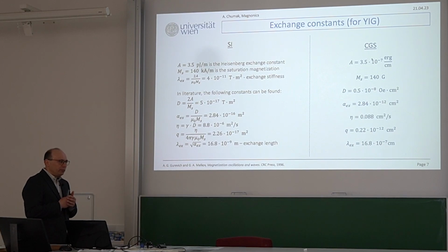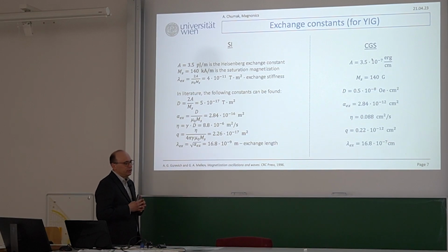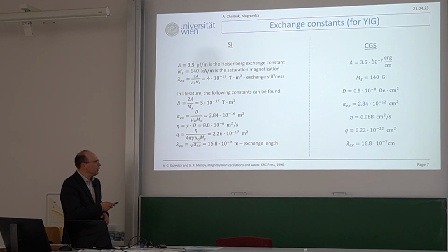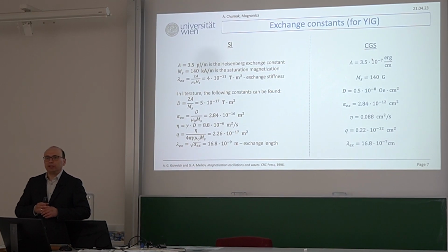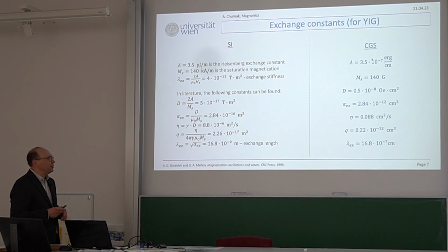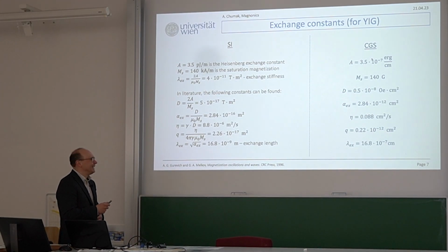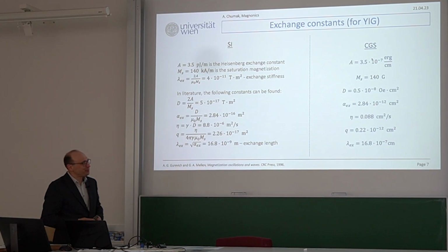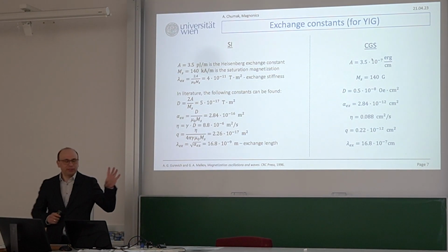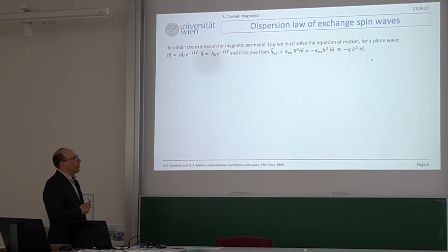It's also important for micromagnetic simulation. Strictly speaking, when you want to do proper micromagnetics, your unit cell should not be larger, or shouldn't be much larger, than the exchange length. Is it correct, Andrii? Good. Andrii is our expert. He was trained by Dieter Suess and Claas Abert. He knows. Good. So here you see some values in SI and CGS. I hope this simple collection will help you, but still don't hesitate to double check everything carefully, because sometimes it's a bit messy in the literature.